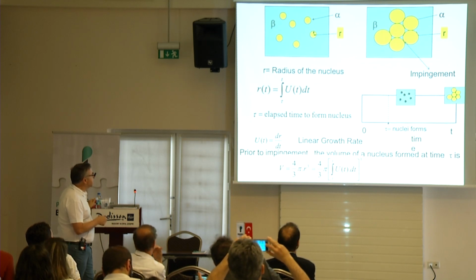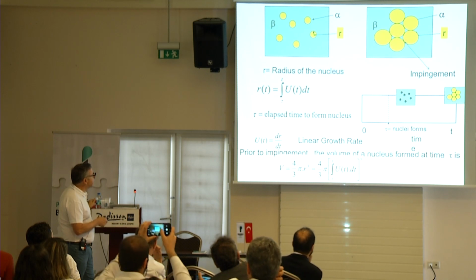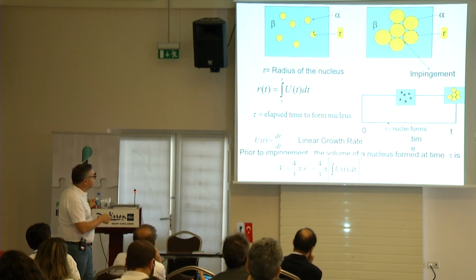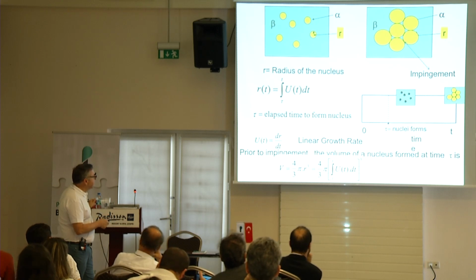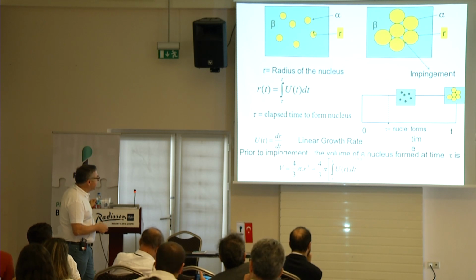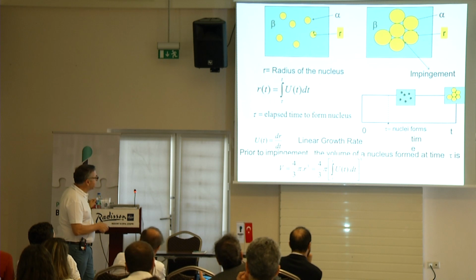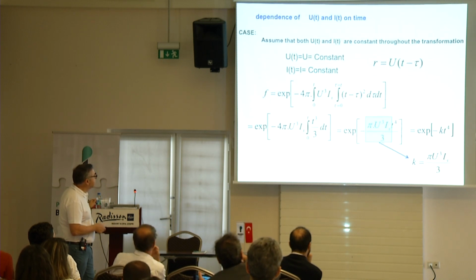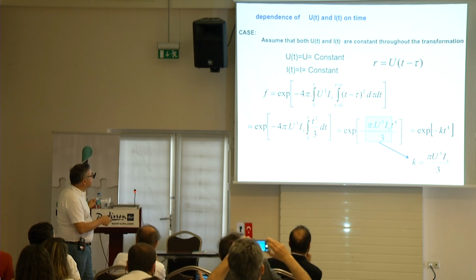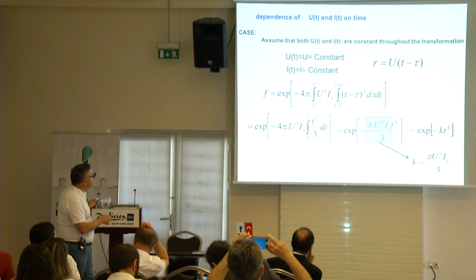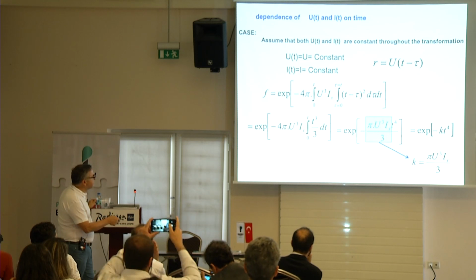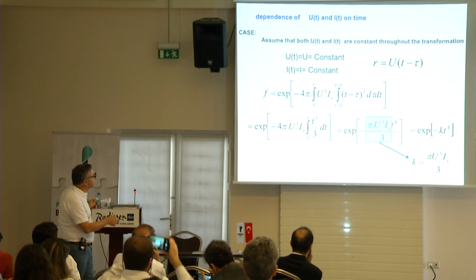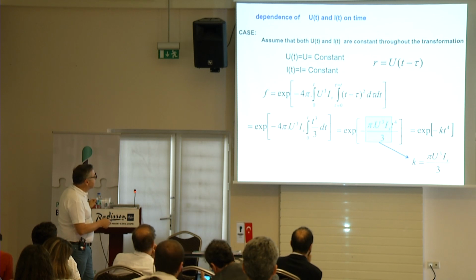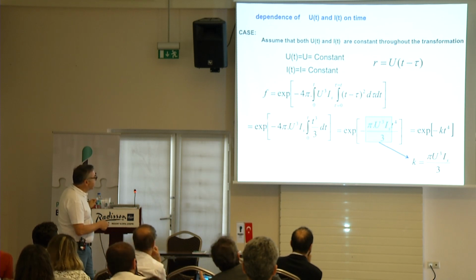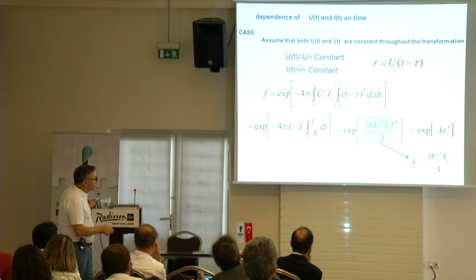But this is the growth rate. You can simply determine the size of it at a given time, from tau to whenever the time is. It's a relatively simple integration, and you can get that. And if your crystal is a volume, you have basically a sphere, you can get the spherical information and plug all that in, and so on. At the end, I just don't want to bore you with all these things. You can assume the constant growth rate and the nucleation rate is constant. So this is how you determine the radius of a given crystal, relatively simple. Plug it into this expression, and what you get is a very powerful kinetics equation. This is called crystallization kinetics.